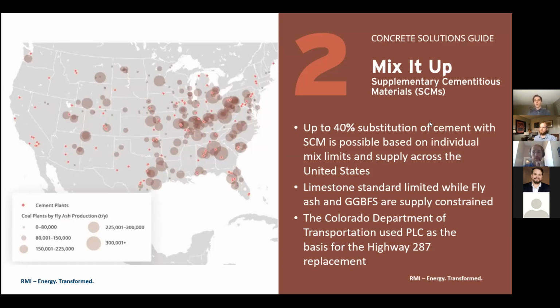Fly ash provides probably the most opportunity for upside in terms of increasing the amount of SCMs being used. So there has been a decrease in the amount of fly ash that's available, and that's associated with coal-fired power plants obviously being shut down. And that's what you can see in the map here, what's remaining in terms of coal-fired power across the US. And that's led to some regional differences as well. So you can see on that map that there's still quite a lot of coal-fired power and therefore fly ash available in the east, but less so in the west. And in Colorado specifically, there are still a couple of large coal-fired power stations, including the Comanche power plant.